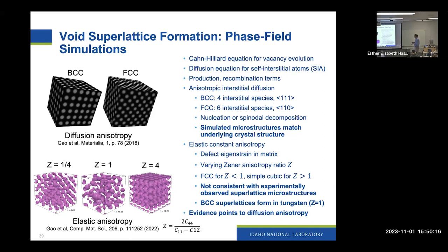The thing with this is that the simulations in this case are not consistent with the experimentally observed microstructures. And another fact that I think is important here is that it has been observed that in tungsten, which has a Zener anisotropy ratio of 1, you still form BCC superlattices. So a lot of the evidence that we see from this work points to diffusion anisotropy as the main mechanism for how these superlattices form.